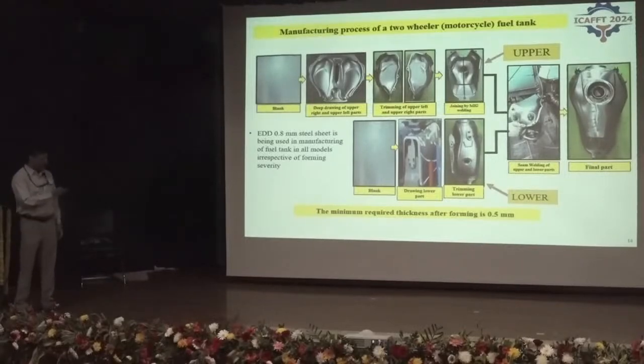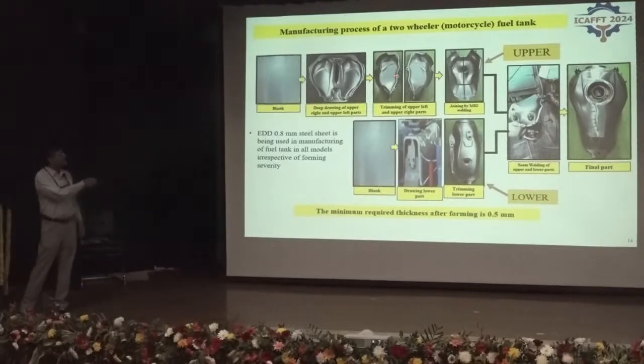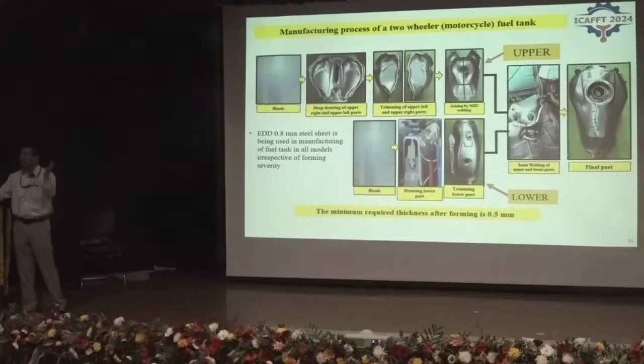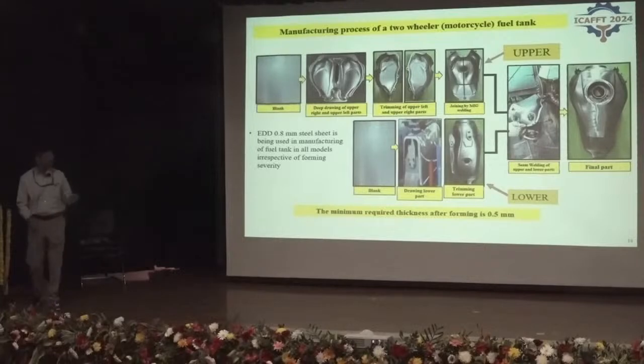regulations. Okay, so one is by reducing the initial sheet thickness with the same grade. What is the minimum thickness at which it can be produced? And if we change the grade to a better grade with better formability, then what will be the minimum sheet thickness with which it can be produced? And the third option is, instead of making these two parts separately, whether we can make the entire fuel tank in one single step using an alternate manufacturing process, that is hydroforming. So these are the alternatives that we just explored.